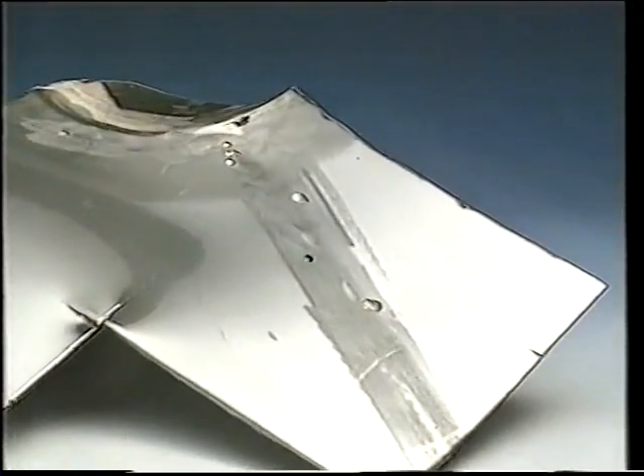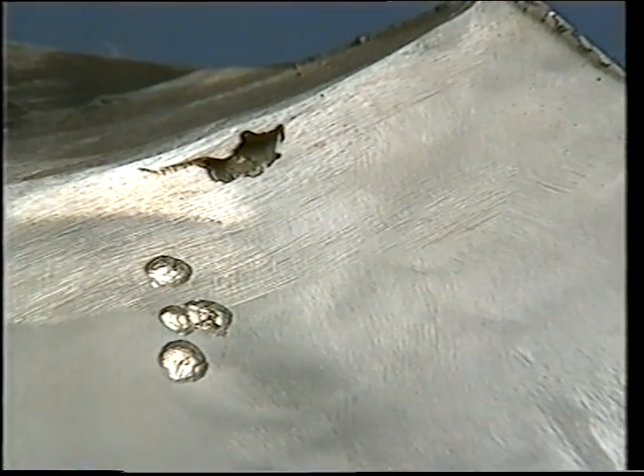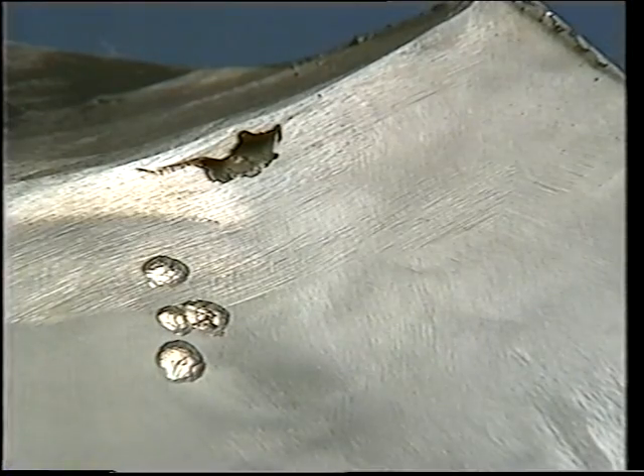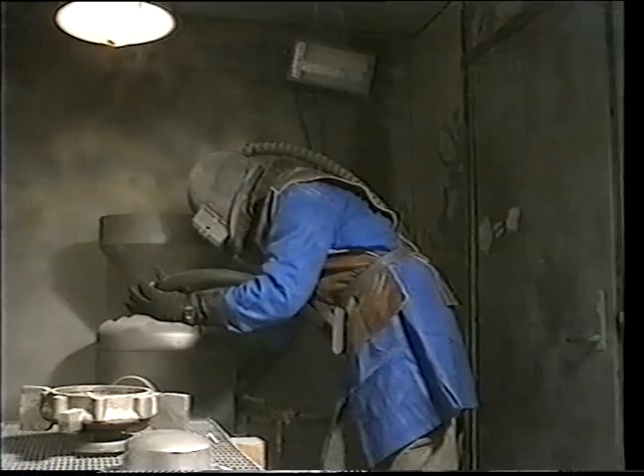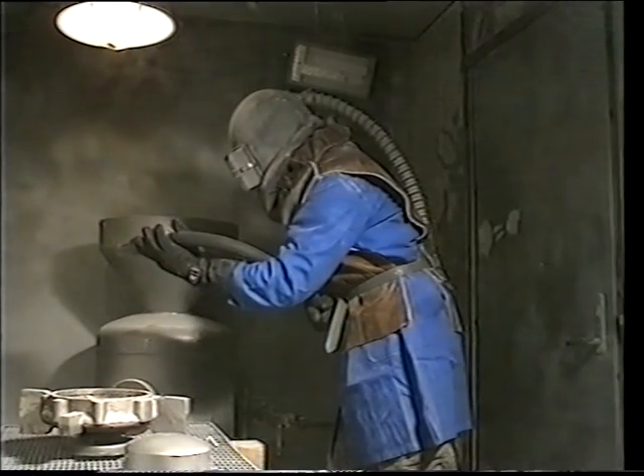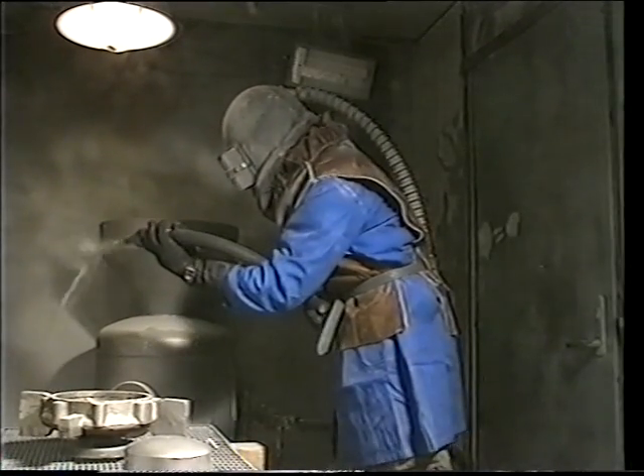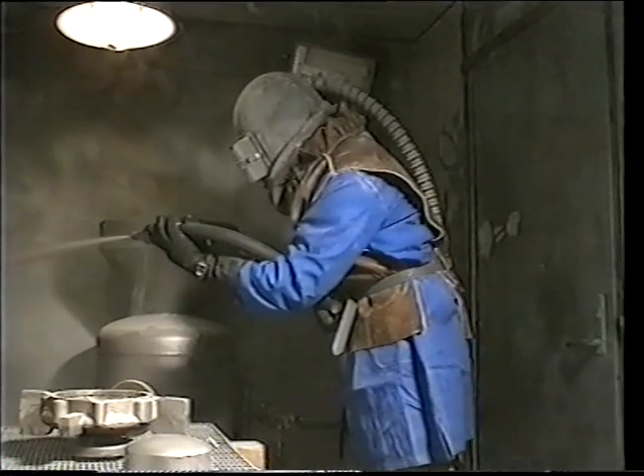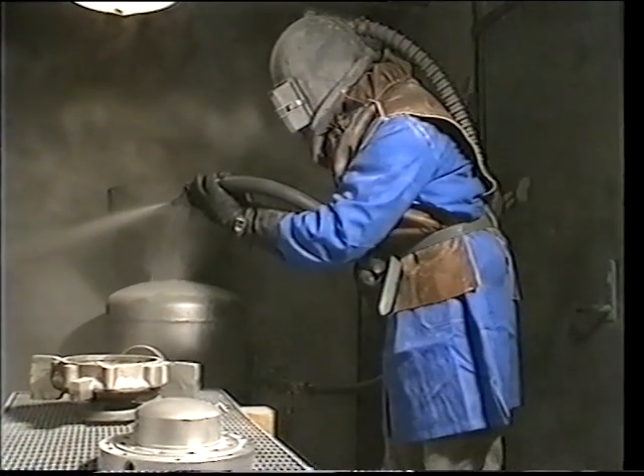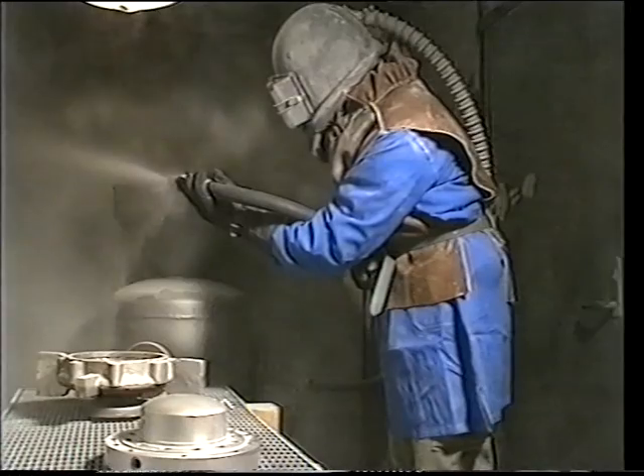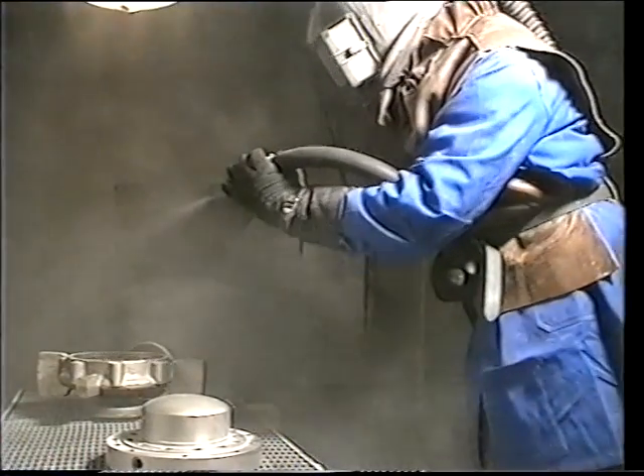This real-world example shows pitting corrosion on the ground surface of a wine tank. After only a year, it has perforated the tank, allowing wine to leak out. So let us consider a different surface treatment. Blast cleaning, using iron-free media, of course. Glass bead blasting, for example, not only cleans the surface, but also converts any existing tensile stress into compressive stress. That reduces the risk of stress crack corrosion.